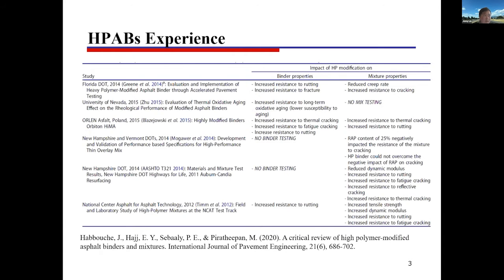In the past decades, asphalt binders have been modified using a wide range of polymer modifiers or technology to achieve the desired properties. And polymer is the most commonly used asphalt modifier. So what is an HPAB, a highly polymer-modified asphalt binder? Basically, this type of binder has a very high polymer concentration, about 7% of the asphalt binder.